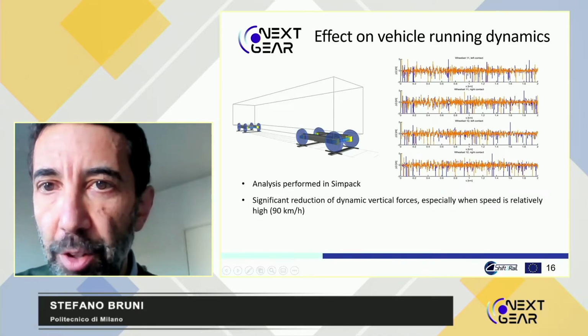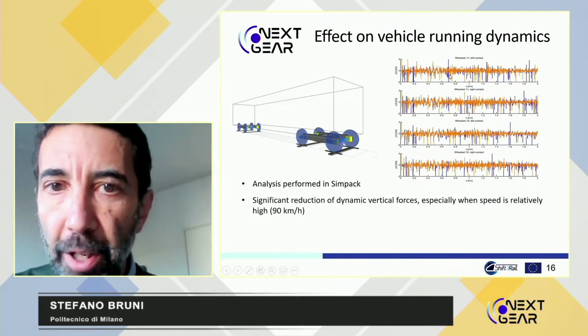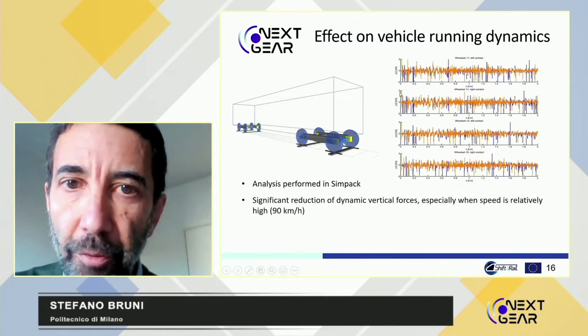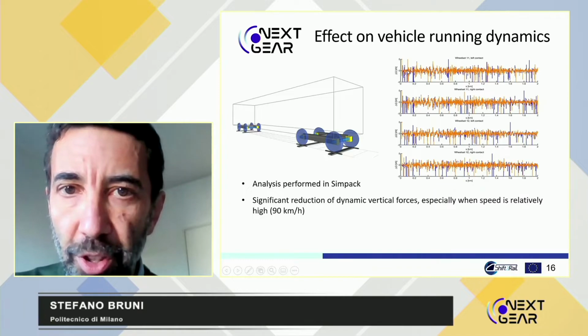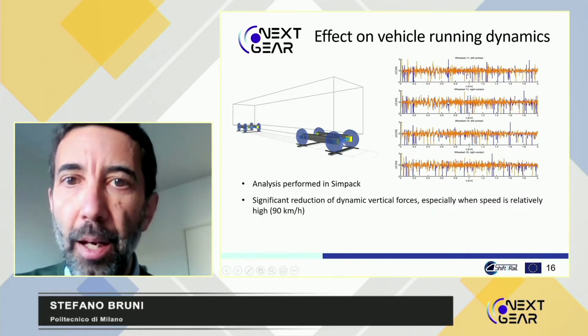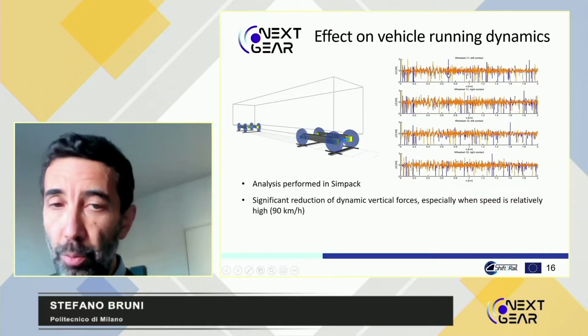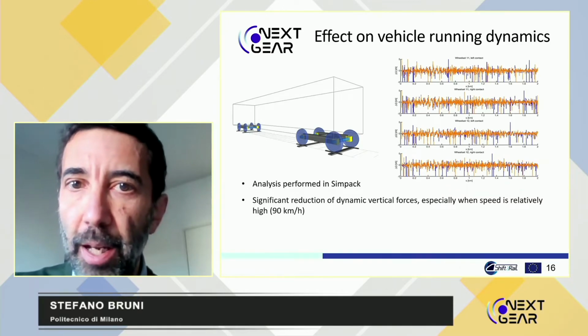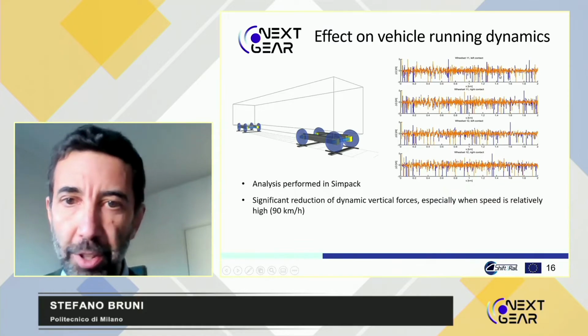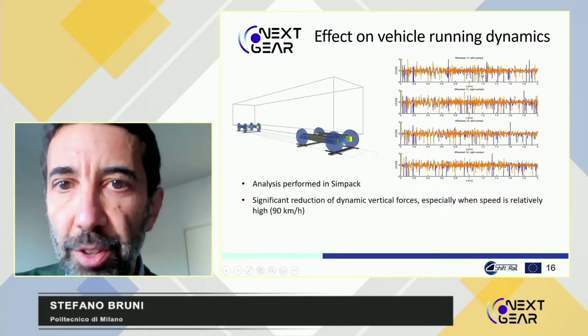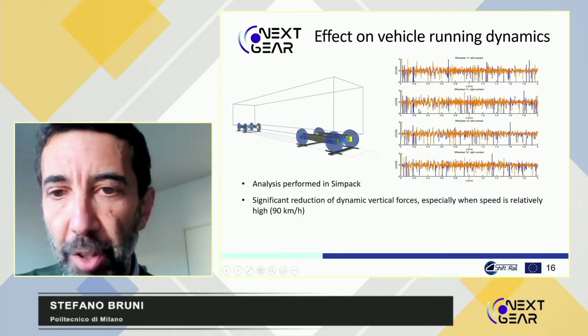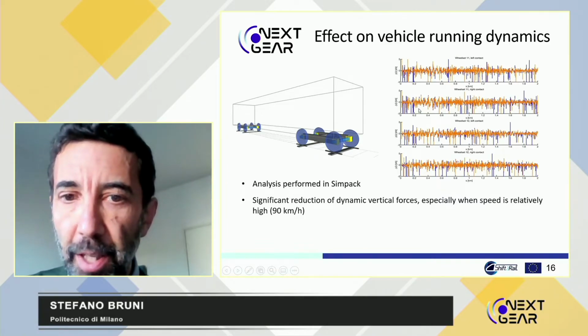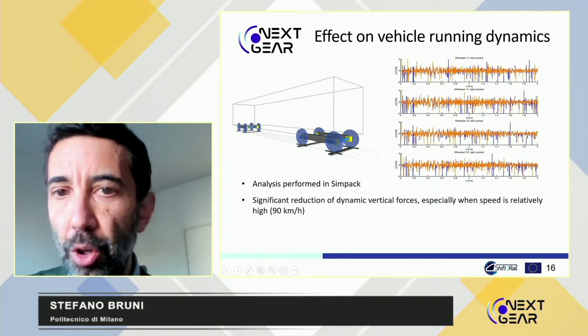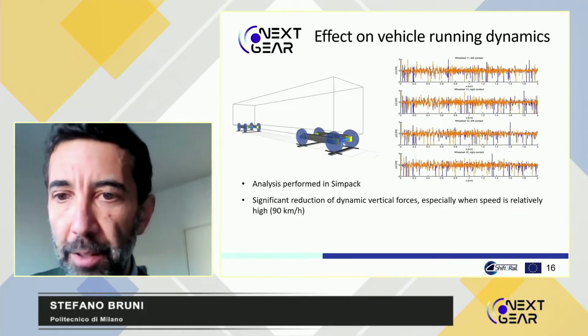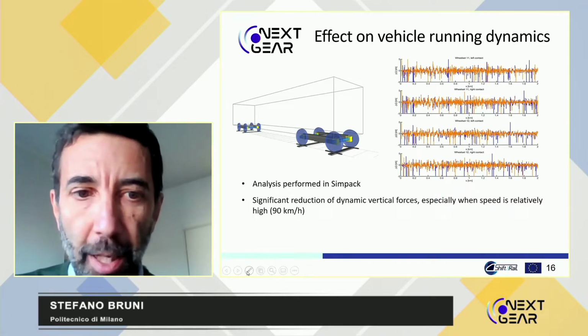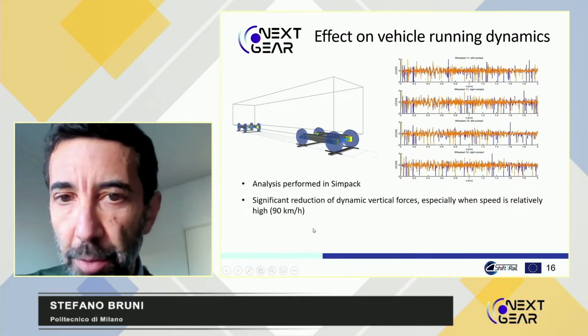In this sample result, you see in orange and blue the variations of the vertical wheel-rail contact force at the four wheels in one bogie. In orange, the result for the new wheelset with the lighter axle, and in blue, the result for the wheelset with the reference steel axle. You can visually see a significant reduction of the maximum dynamic vertical forces. This is, of course, more relevant when the speed of the vehicle is relatively high. So we went up to a maximum speed of 90 kilometers per hour.